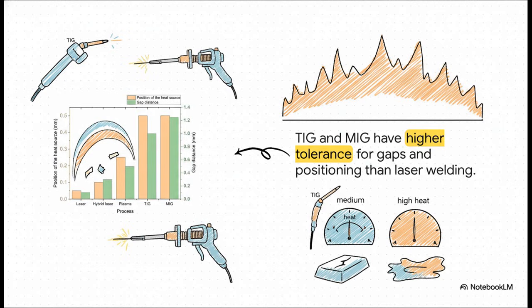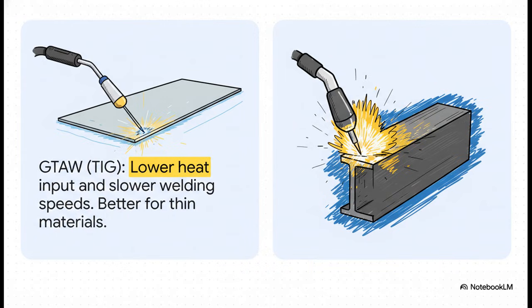But here's the real kicker. The total amount of heat they pump into the metal is vastly different, and that has huge consequences for the final weld. TIG is the undisputed master of low and slow. It uses lower heat input, which gives the welder amazing control, and that makes it perfect for really thin materials. The trade-off? It's slow. MIG, on the other hand, is the speed demon.